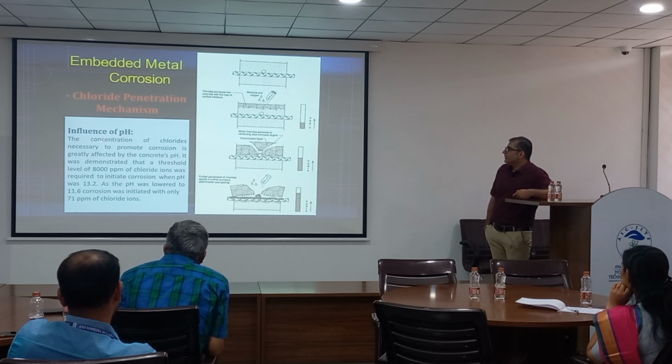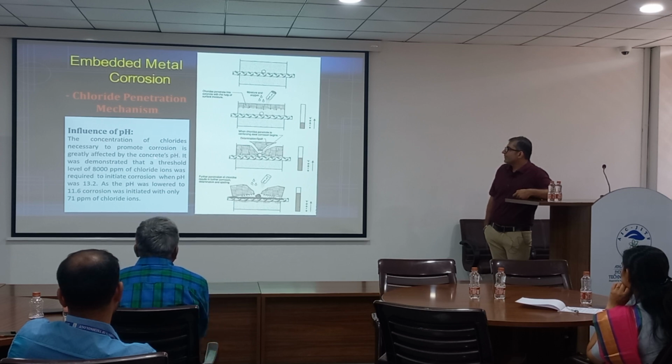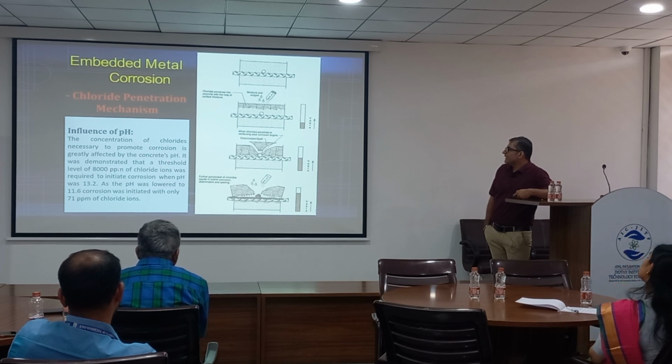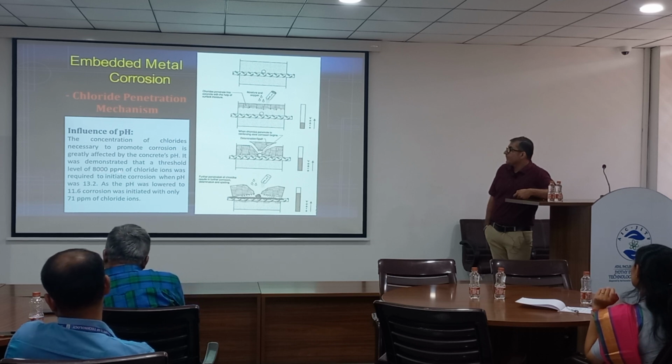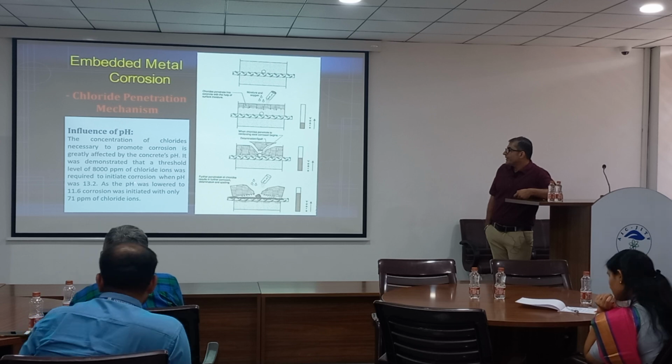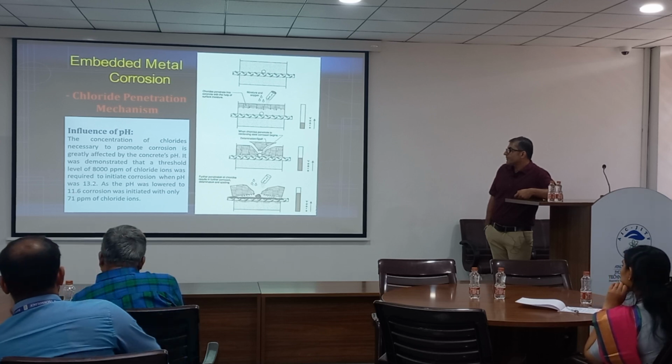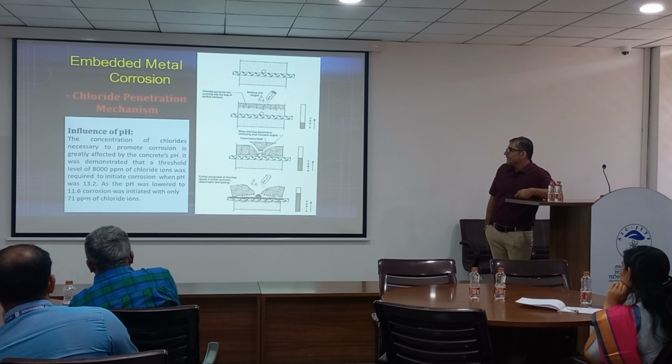Okay. So, I think it has been mentioned here, the concentration of the chlorides is greatly affected by the concrete's pH, right? It was demonstrated that the threshold level of 8000 ppm of chloride ions was required to initiate corrosion when the pH was 13.2. So for the corrosion process to initiate, 8000 ppm of chloride ions was required, right? As the pH was lowered from 13.2 to 11.6, for the corrosion process to initiate, only 71